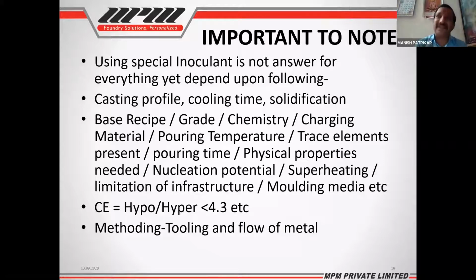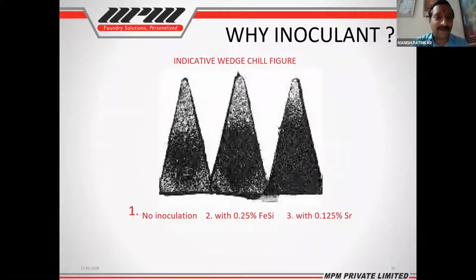Ultimate answer, if nothing else is there, then only 1% is the possibility where inoculation can add something to the performance. If you have a direct shrinkage, believe me, 99% inoculant will not work. If you have a micro shrinkage, very minute, because of fading or something similar, then yes, that's an answer. So what exactly is the inoculant?